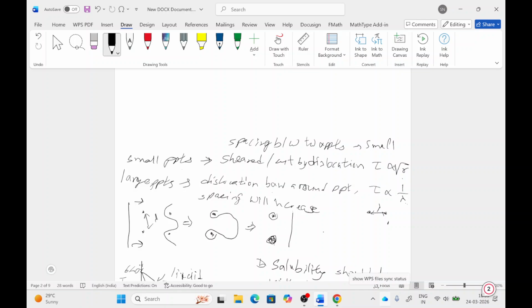This dislocation loop can further result in generation of more dislocations, meaning a point of dislocation generation. So the dislocation surpasses, and after that, the dislocation loop remains on the precipitate.